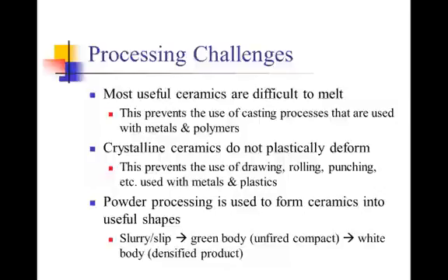But we can't do that to ceramics either, because they don't plastically deform. Those dislocations can't move within the ceramic crystals. And so the properties of hardness and high melting point that are so advantageous to ceramics in some applications become real hindrance in getting them into a new shape.